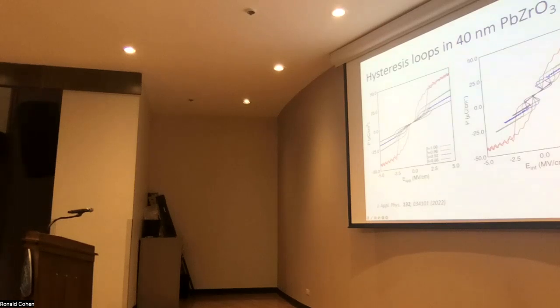So we simulate different amount of surface charge compensation. We go from full charge compensation, ideal short circuit boundary conditions, and then we make charge compensation worse and worse and worse. And this is what we find. This data report the polarization response to the applied electric field. And as you can see, no matter what we do, we never find negative slope. But now if we report the polarization response to the internal field, which is once again the superposition of the applied and depolarizing field, this is when we see the emergence of that negative slope, of that negative capacitance regime.